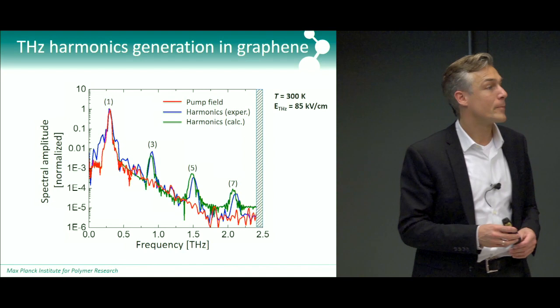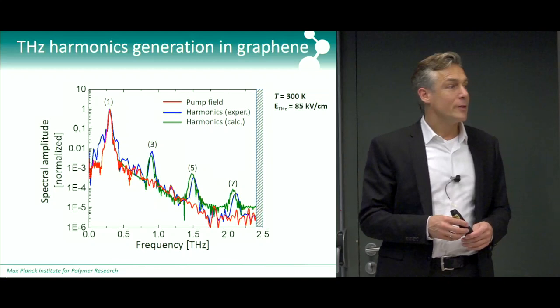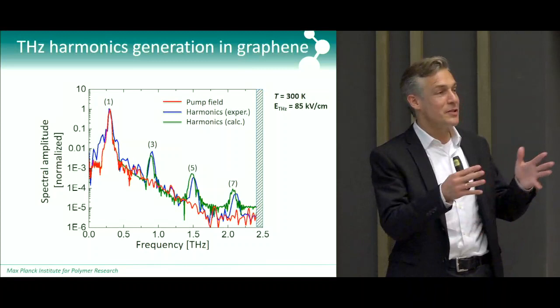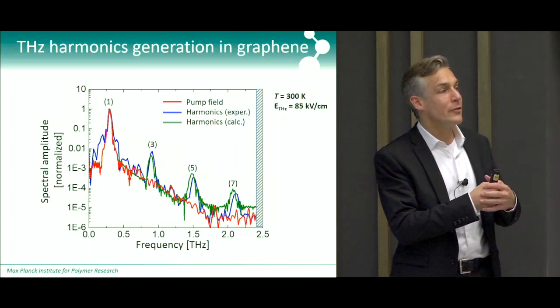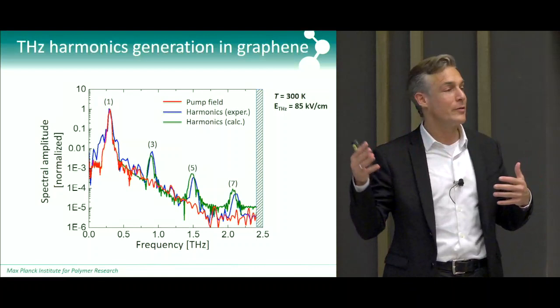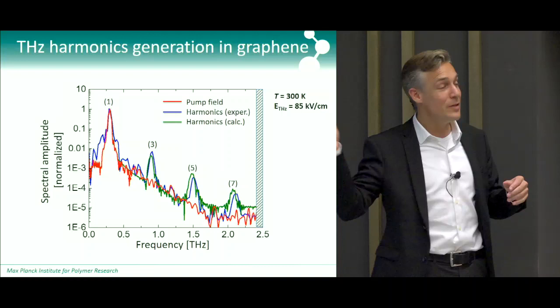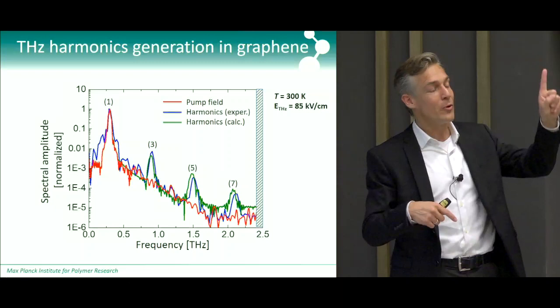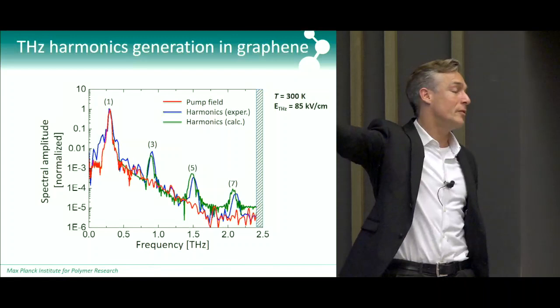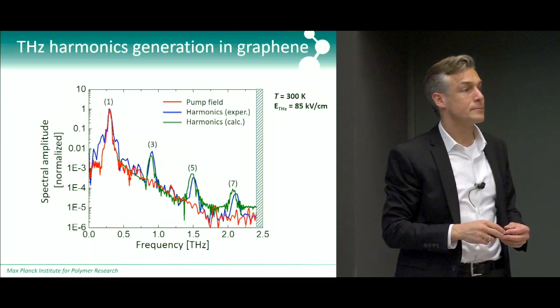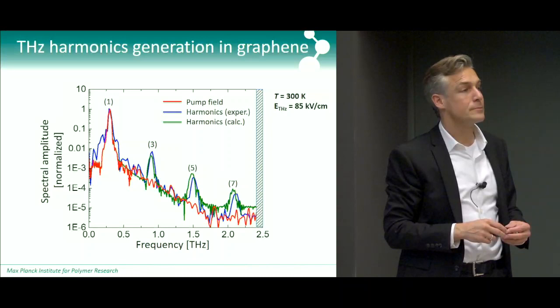Q: You see only odd harmonics — can you get even harmonics? A: No, you cannot get even harmonics because of symmetry. Graphene is a centrosymmetric material, so the second and fourth harmonic signals are not dipole-allowed. You generate locally very high even-order polarizations, but for each polarization created in one direction there is another that cancels it, so in the far field you see nothing.